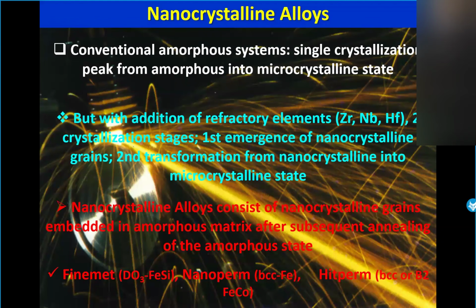So at the end of the 80s, Yoshizawa and his group in Japan found a new family of systems, which have been called nanocrystalline alloys. Typically, maybe you heard about Finemet, Nanoperm, Hitperm. The main characteristic is that they present 2 crystallization peaks. After the first one, you will get some nanocrystalline grains embedded in an amorphous matrix.